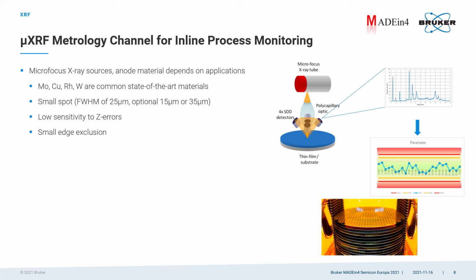The beam comes from 90 degrees above the sample, and therefore the setup has a low sensitivity for errors in sample height. The small spot allows for measurements basically till the wafer edge, so the edge exclusion is very small. On the detector side, we work with SDD, silicon drift detectors, for efficient photon collection that does not require cooling with liquid nitrogen. We can mount up to 4 detectors in the tool to increase the detected flux.